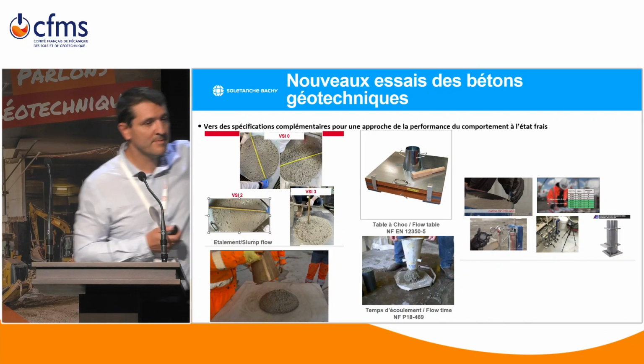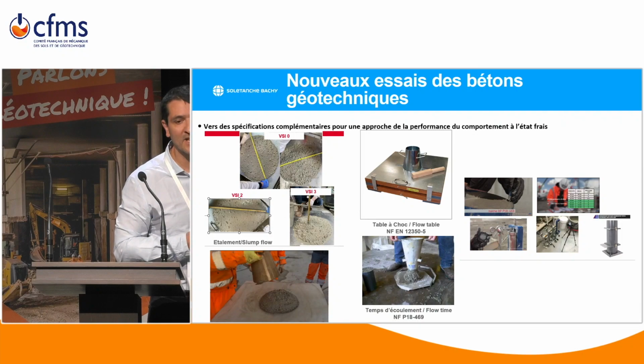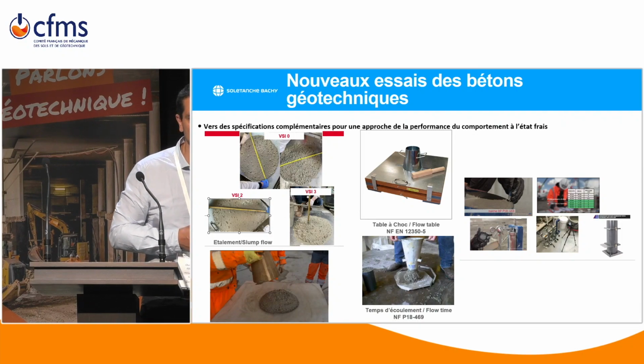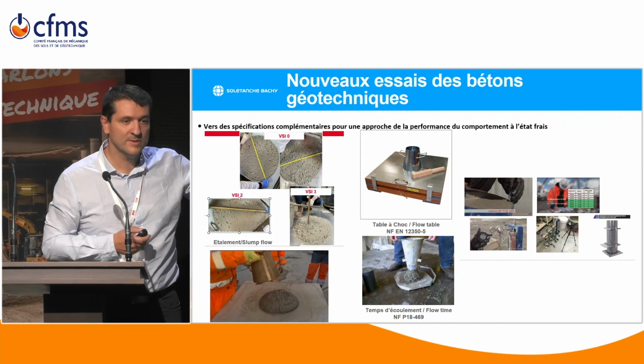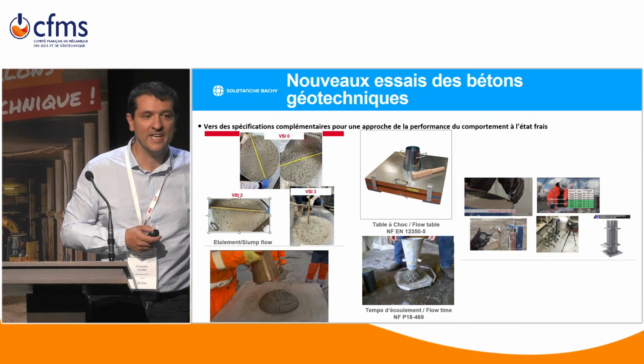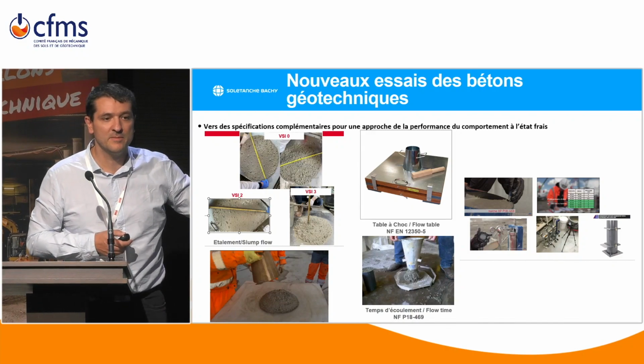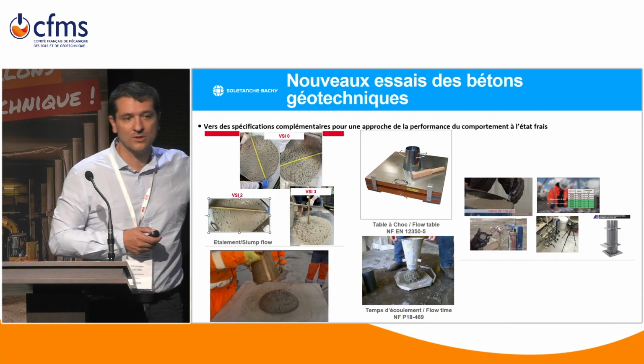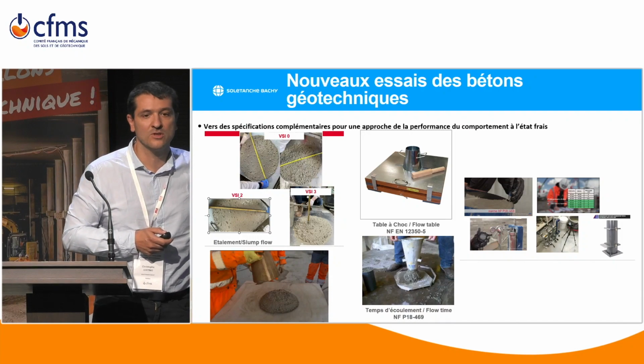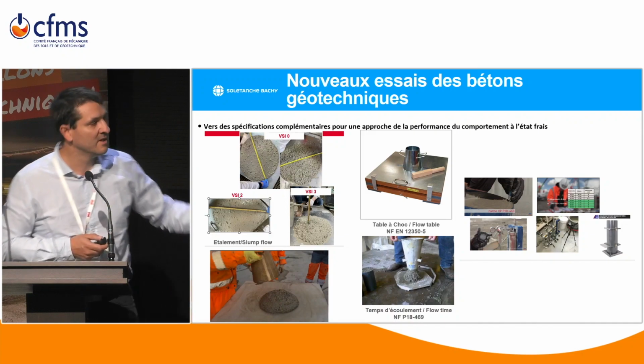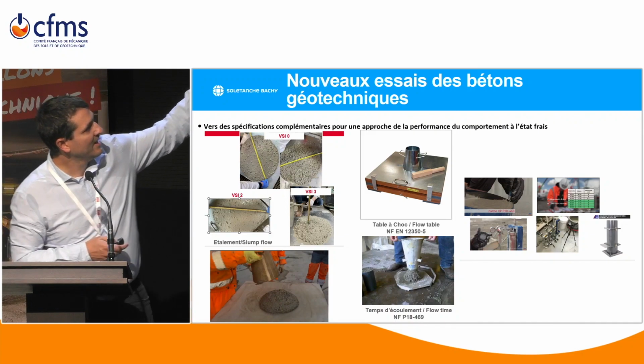It's a major impact because above the limit value that we have, generally, it can change from, let's say, discharging an 8 cubic meter truck in 5-10 minutes to discharging an 8 cubic meter truck in 30 minutes, 45 minutes, just because of the viscosity of concrete. So those are important tools.